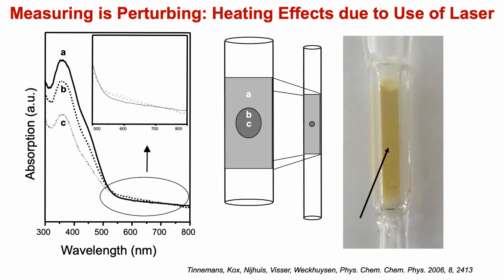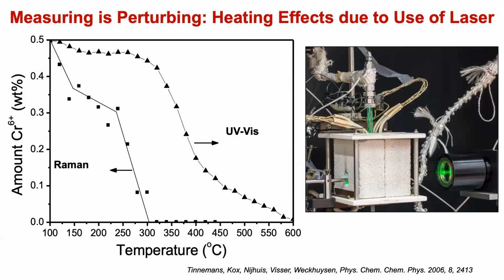And what you notice is that the reduction of chromium-6 to chromium-3 is actually enhanced when you have the laser on, because the laser increases the temperature, hence the reduction goes more easily. So here I show you the offset between Raman on, and you see how easily the chromium-6 reduces because you put extra temperature in it, compared to UV-vis. So two techniques: you use a second technique to check the first technique. It's very important to do that.